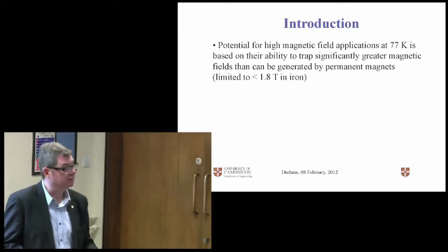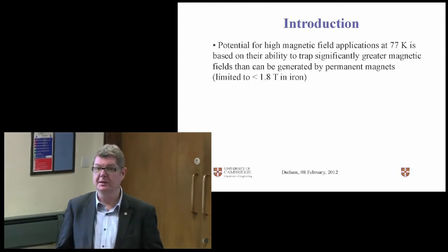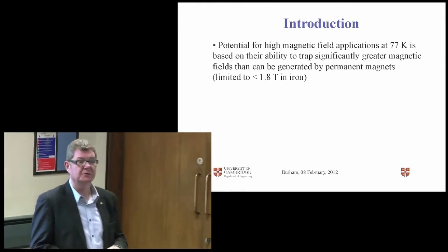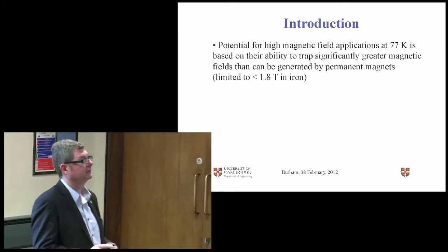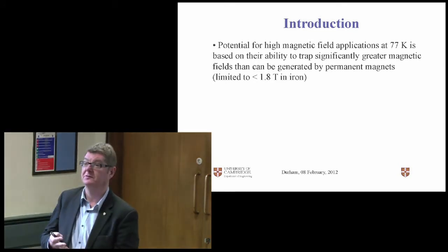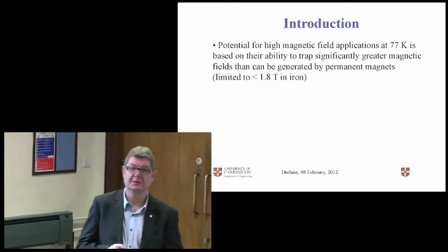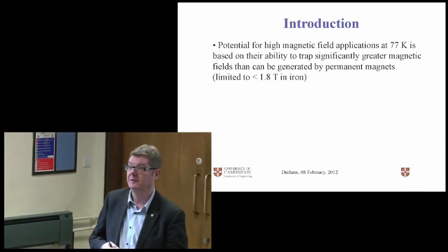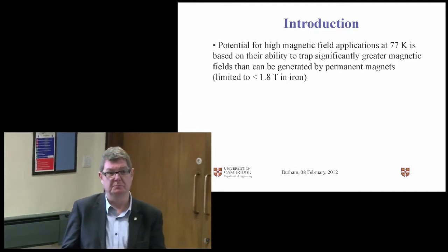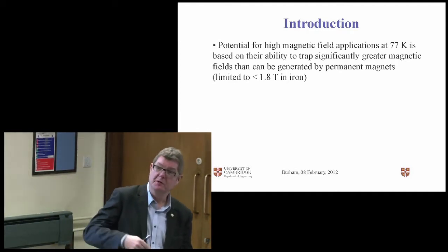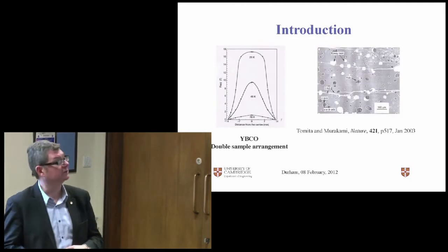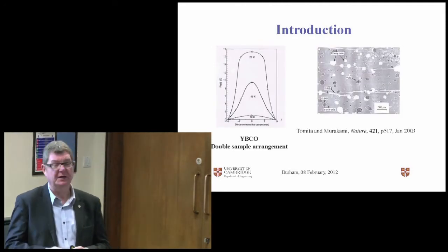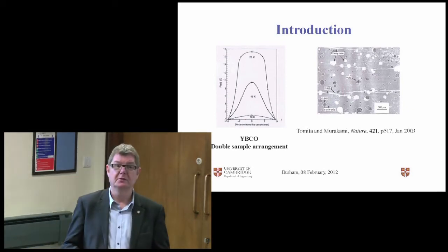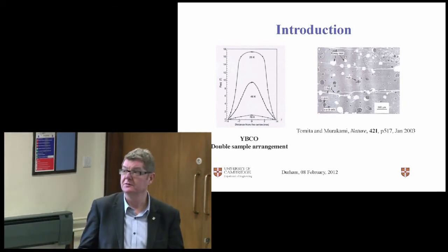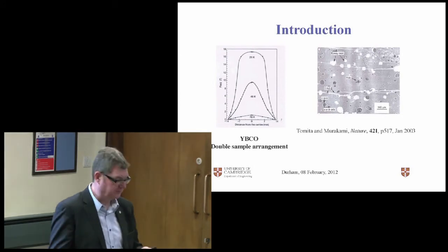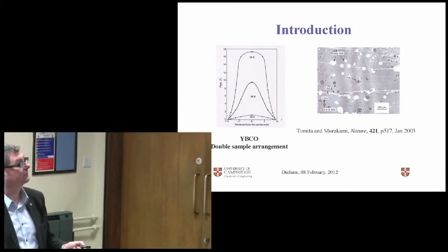Unless somebody finds a new material, and it's very unclear to me where that may come from, then these are the fields you're competing with. The second point to make is that if you have two permanent magnets, a north pole against a north pole, that repulsion or that interaction is intrinsically unstable. In fact, if you leave a north pole being levitated by a north pole, the top one will flip over and north-south will attract and minimise the energy of the system. So permanent magnets, not only do they have a limited maximum field, they also have this intrinsically unstable interaction with one another. Unless it's north against south, which is not levitation.